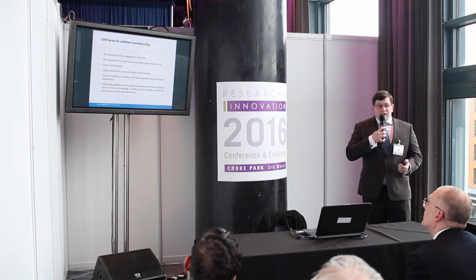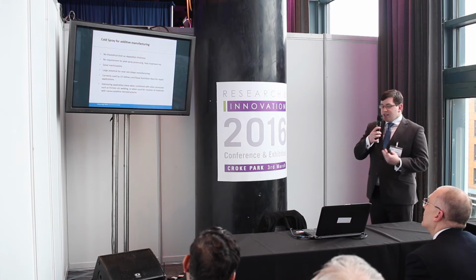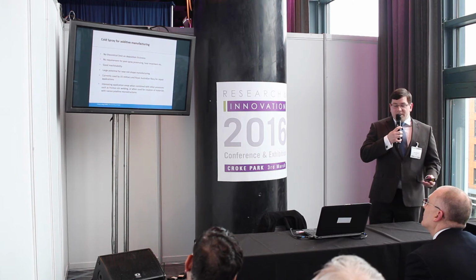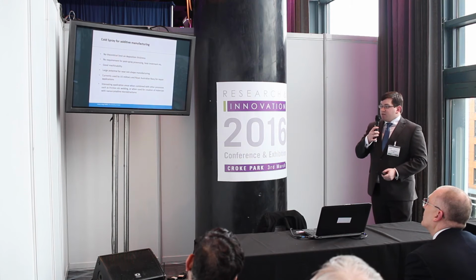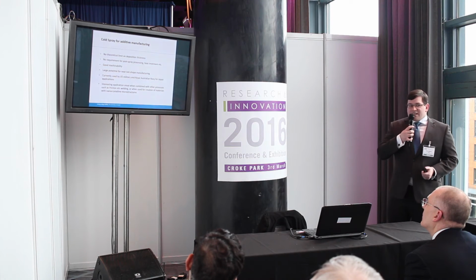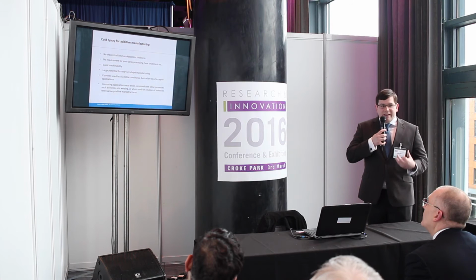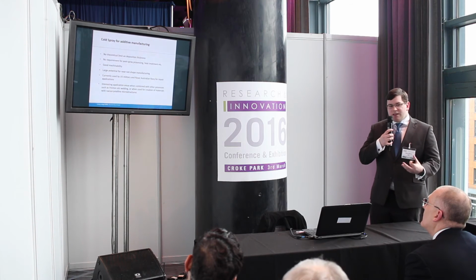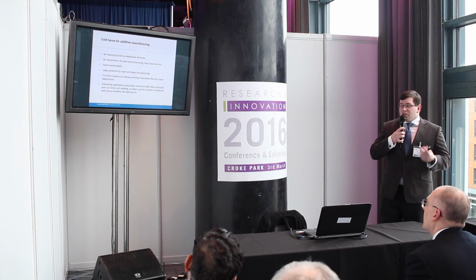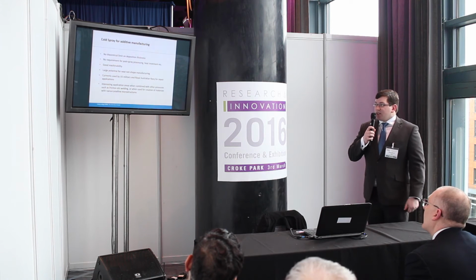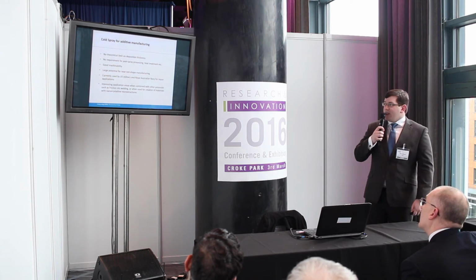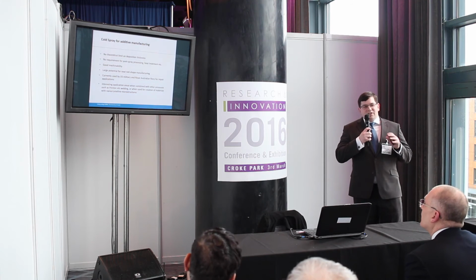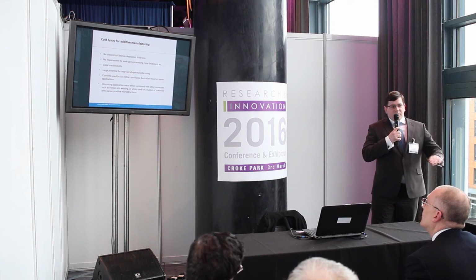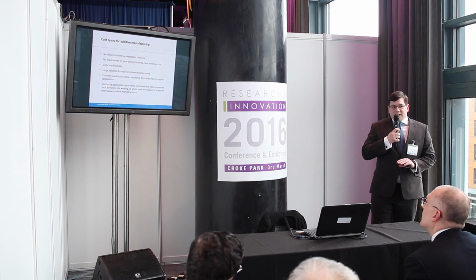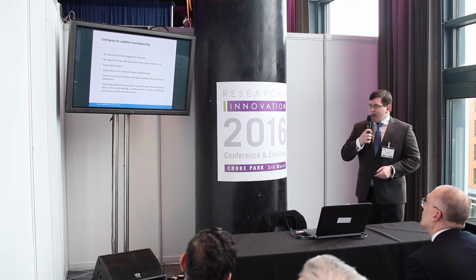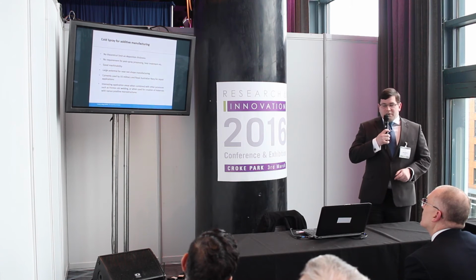The coating is generally very machinable, very easy to do finishing processes on it, polishing. So there's very large potential here for near net shape manufacturing, where you use cold spray to deposit a very dense layer of material selectively, then you machine that down afterwards to make what you're looking for. And cold spray is currently used by the US military and the Royal Australian Navy for repair applications, and there are also a lot of other interesting applications, such as putting down a layer of cold spray material and then friction stir welding onto that, or some nanocrystalline microstructure applications I'll show you in a minute.